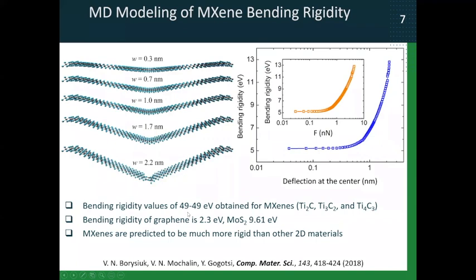And it turns out that bending rigidity values are very, very high. This is the range, sorry, I put the same number twice. Of course, it makes no sense. So it's around 49 to 50 something electron volts for different MXenes. And if you look at these numbers, they are much, much higher compared to graphene. Well, that is expected. Graphene is very flimsy, monoatomic layer, thick material. But even compared to moly disulfide, the numbers for MXenes are much higher. So MXenes are predicted to be much more rigid than other 2D materials.